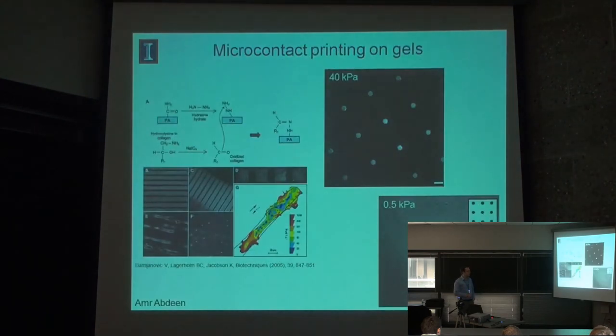And so the question is, can we devise a way to exclusively promote these different fates on these hydrogel materials? And so one way, perhaps, is to use shape, since there's so many different shapes between these cell types. And so we adapted a technique, and this is work done by a student in my group, Amr Abdeen. This is a technique developed many years ago, actually, where polyacrylamide gels are modified with this hydrazine treatment, and then you oxidize a glycoprotein to have an aldehyde that you can then immobilize to the gel. And we developed a strategy to robustly do this across a range of stiffnesses.